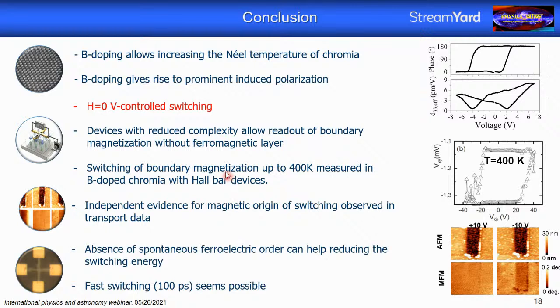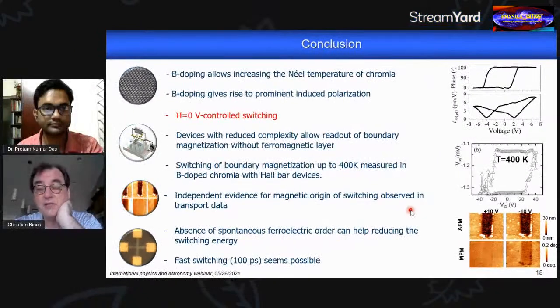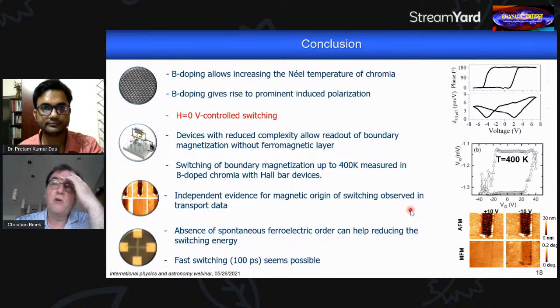And the last remark is that the absence of spontaneous ferroelectric order may in fact turn out to be a major advantage here, because if you look at competing systems, such as multiferroic bismuth ferrite, for example, where you also have an interesting coupling phenomenon between polarization and antiferromagnetic order, their switching speed is limited by the switching of the spontaneous order parameter, ferroelectricity. And we don't have that here. We have induced order, and that could mean a speed advantage.